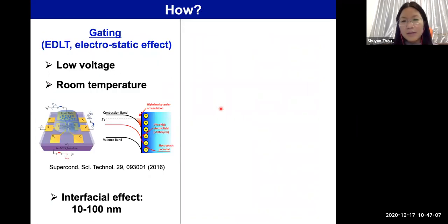So how different is this compared to previous gating of this ionic liquid? We know that for this gating, called EDLT, this is an interfacial effect. It basically acts only in the region within 10 to 100 nanometers near the interface. And for these gating experiments, typically a lower voltage is preferred, and the reaction is mostly at room temperature or even lower, trying to avoid electrochemical reaction.